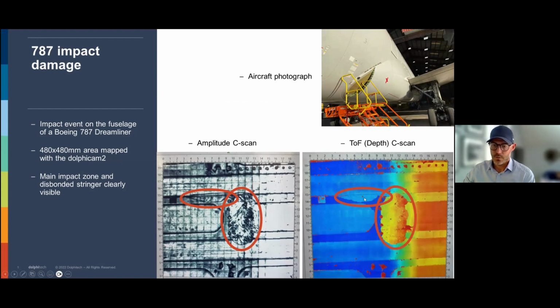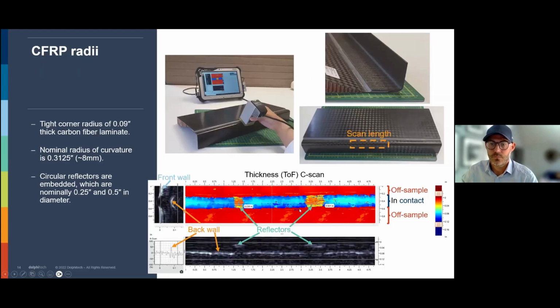But you could also see that one of these stringers detached a little bit, and you have a delamination from this stringer, dark blue. So the dark blue is a little bit thicker, but then you see that the glue came loose a little bit here. This is, of course, a stitched image, which is a lot larger than the transducer itself. So, of course, you can inspect larger areas as well.